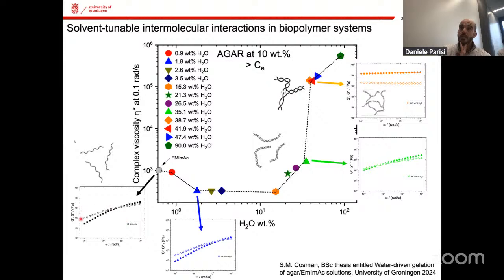So in here we obtain the so-called viscoelastic liquid. Interestingly, as soon as you start adding water, the viscosity drops. Meaning that the agar chains are still far apart, as I sketched over here, and the water is just interacting with the ionic liquid. It's just lowering the viscosity of the dissolving medium, because the water has a much lower viscosity compared to the ionic liquids. But as soon as the agar chains are able to interact with water as well, they start forming these double helices. Okay, and the viscosity starts increasing again, until a certain point, where the viscoelastic liquid is replaced by a weak viscoelastic solid.